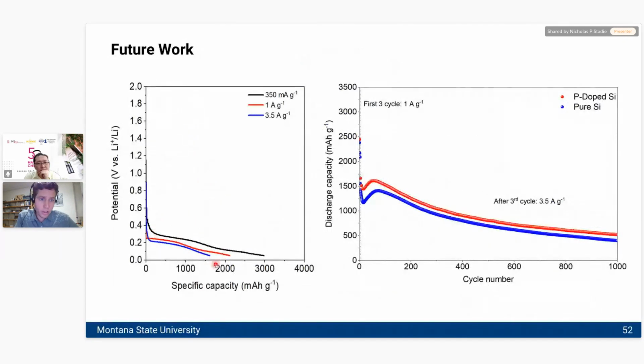Other future work in our group, we're looking at higher charge and discharge rates. So silicon, it turns out, is a very, very fast material compared to graphite, and that's on its side as well. So you can actually do rapid charging with silicon at extremely fast rates, and our group is looking into that. This slide is actually not the best representation of that.